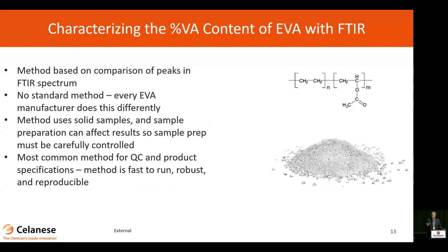So the method's very robust, but if you go from one manufacturer to another, the methods won't necessarily be the same. The other thing is these methods use solid samples. So the sample preparation can in principle affect the results of the measurement. So again, the sample preparation has to be part of the validation, carefully validated to make sure you get the right results. But on the other hand, this is a very fast method to run. It can be run quickly, many times. It's really good for product release and good for product specifications.